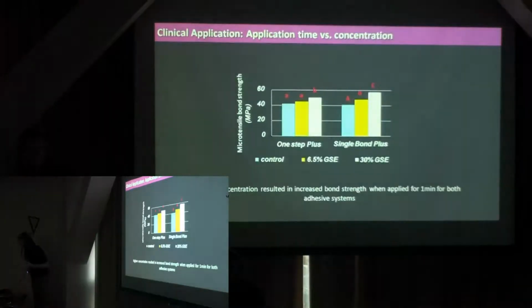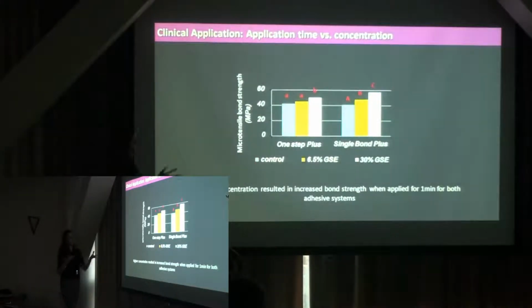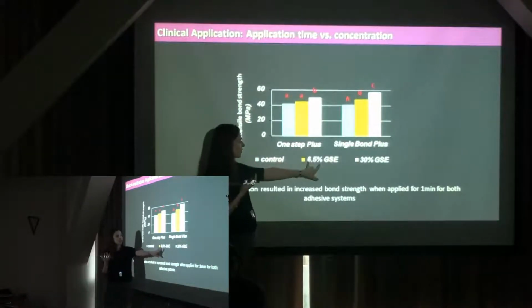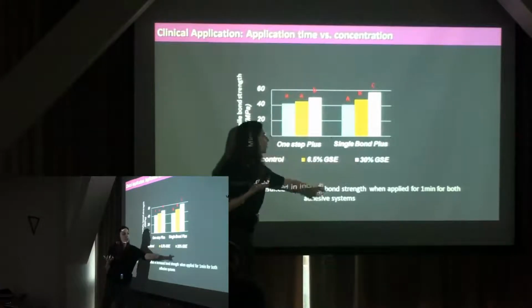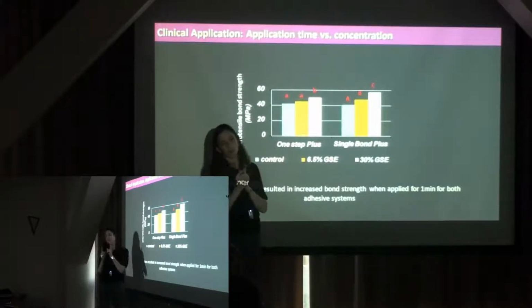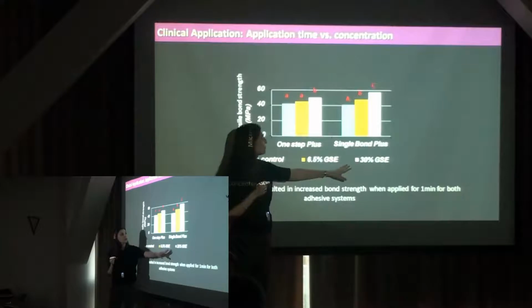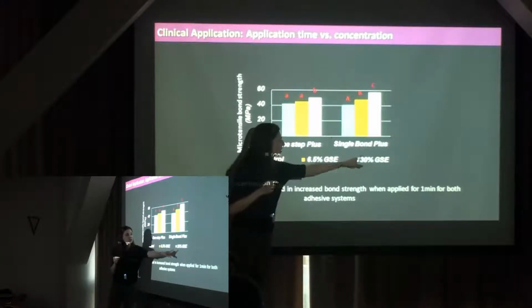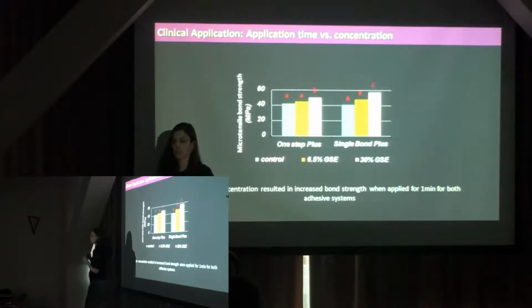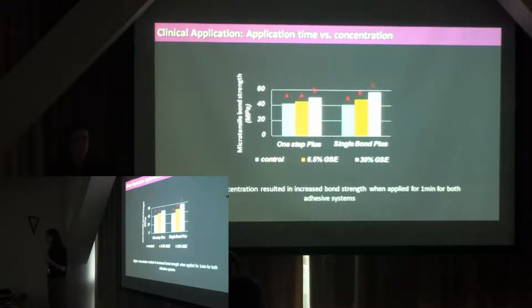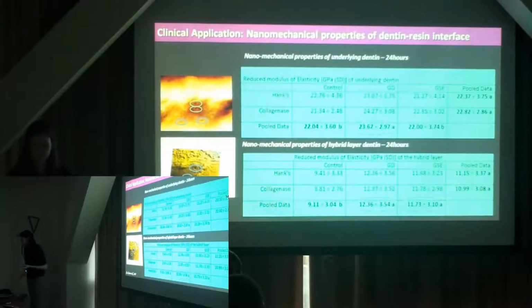And what you see, unique to the grapeseed extract, is that the higher the concentration, the quicker the response. So we compared the usual concentration that we use versus a 30%, and we used it for a 1-minute application. When we use a 1-minute application, you see only a statistically significant increase with the 30%. So we know that we need to use a higher concentration. That would not have been true for the other compounds.